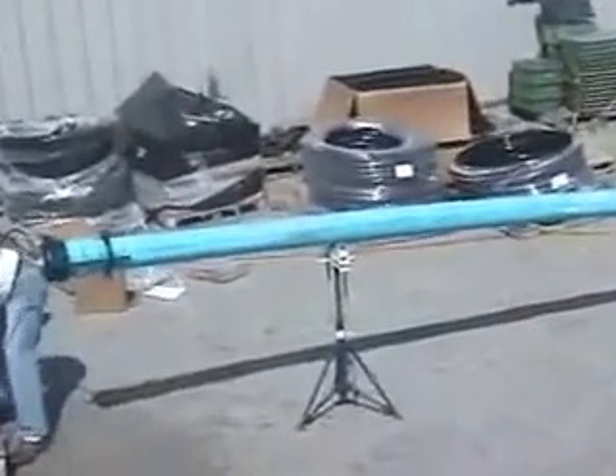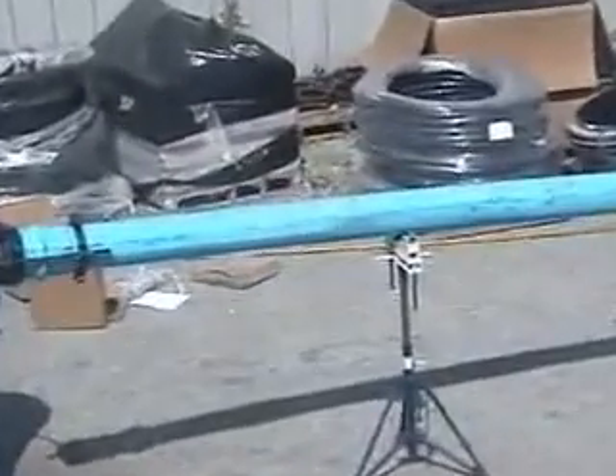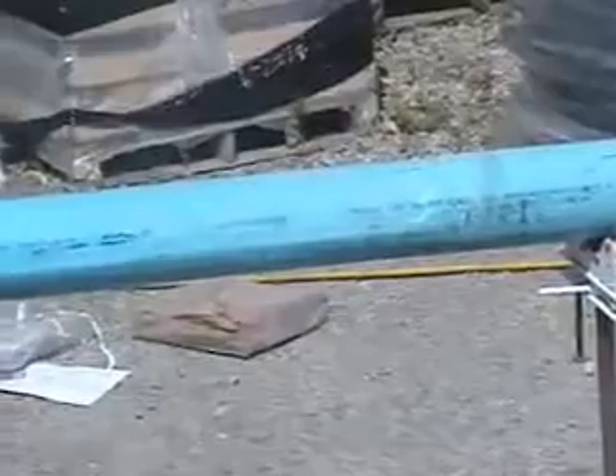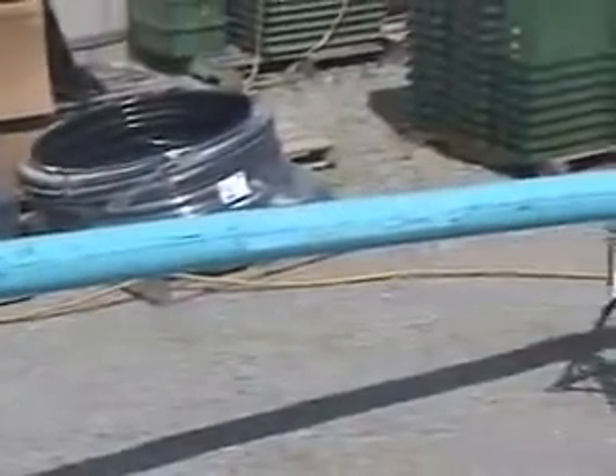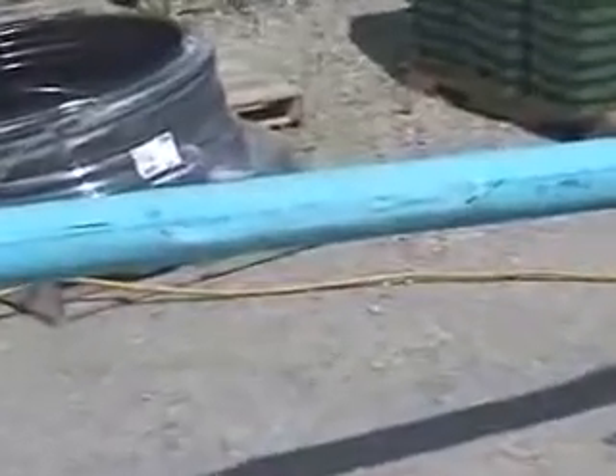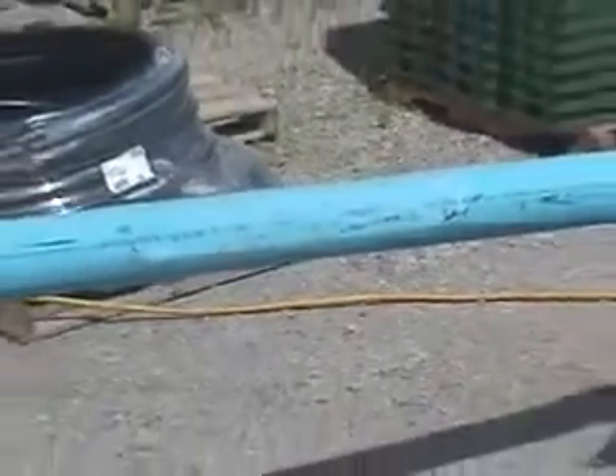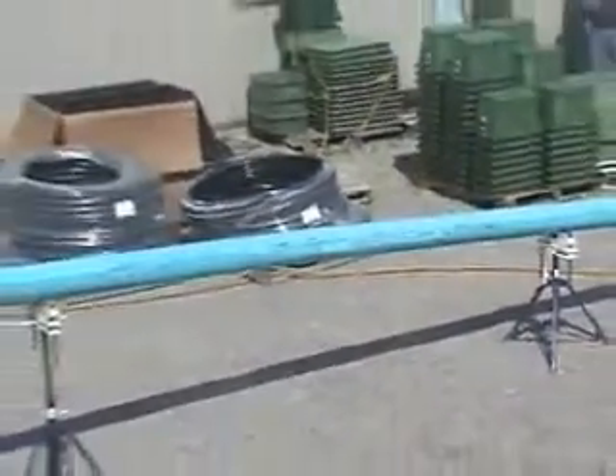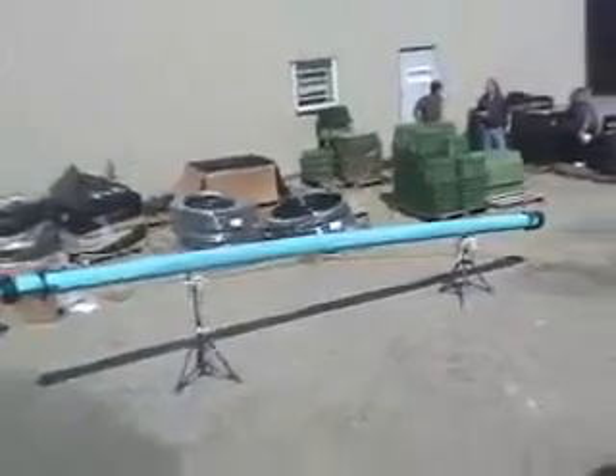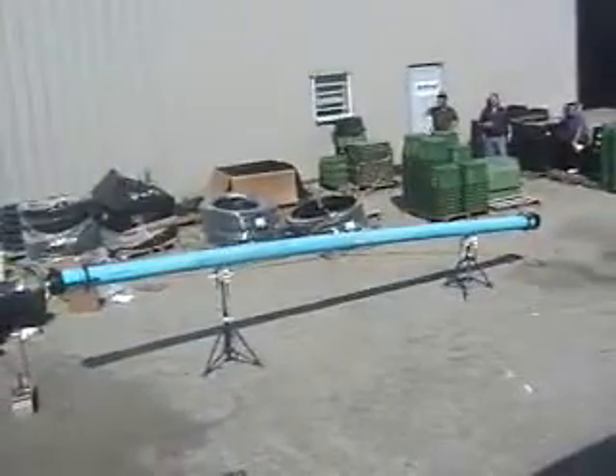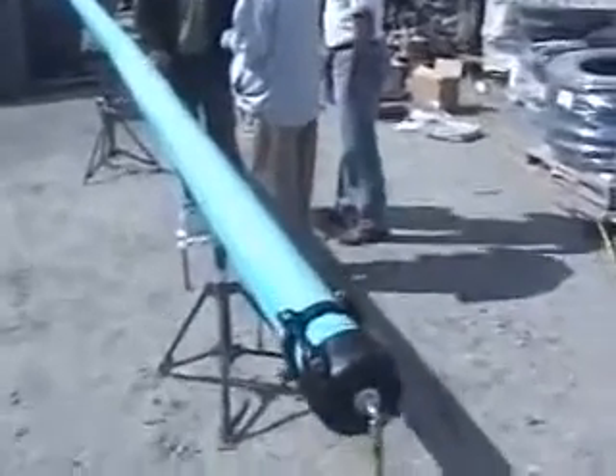This piece of Bionax is pressure rated to 235 psi. We pressurized it to 260 psi and it passed. You can also see the pipe re-rounded itself. Subsequent to this test, this piece of Bionax was pressure tested to 500 psi at our Langley IPEX manufacturing plant.